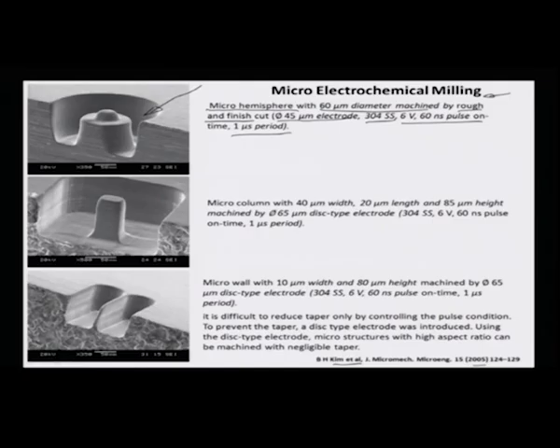Similarly, this is another example where a micro column has been machined with a width of 40 microns, 20 micron length and 85 micron height. So, very high aspect ratio has been machined by a 65 micrometer disc type electrode. And this is again an example of milling where the electrode is rotated, because of which there is machining taking place at this nanometric level. So, a 304 stainless steel electrode is used in this case with 6 volt, 60 nanosecond pulse on time duration and a 1 microsecond period. This is another illustration, of a micro wall with 10 micron width.